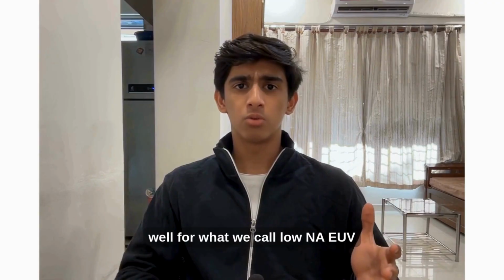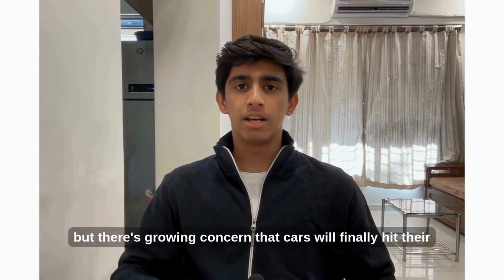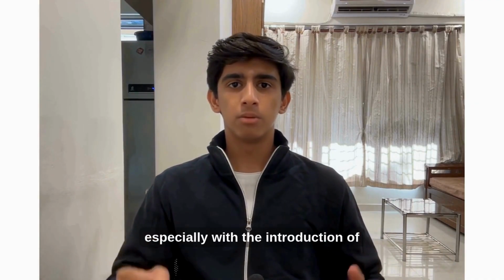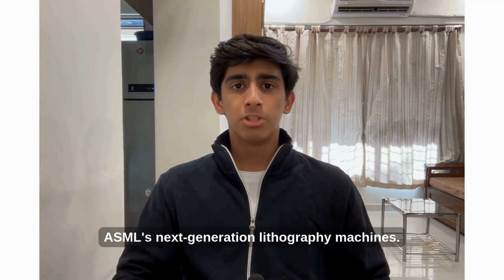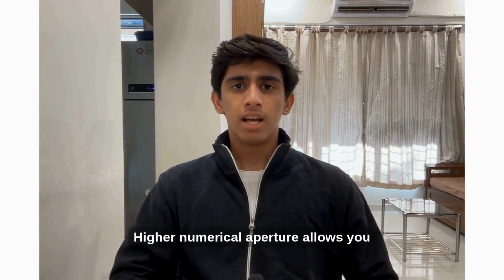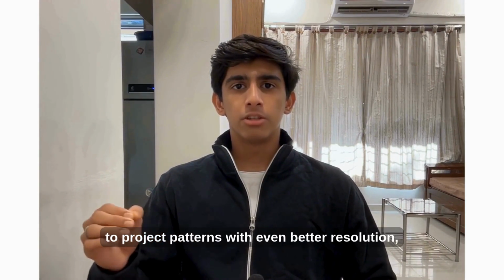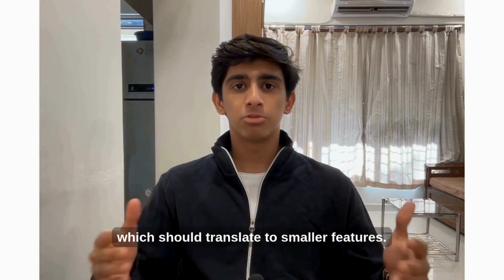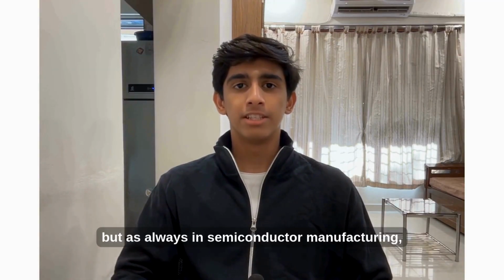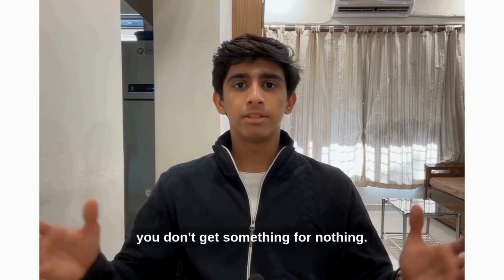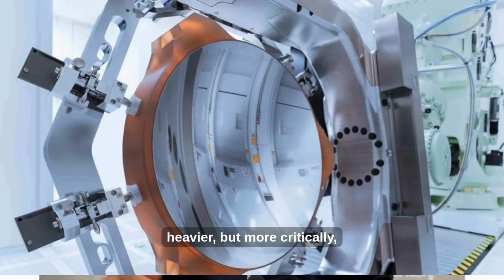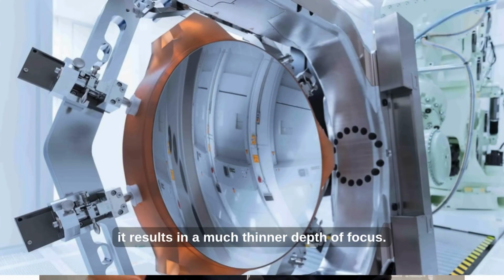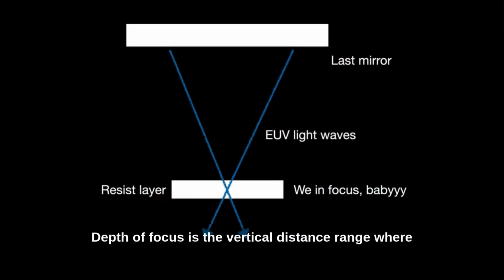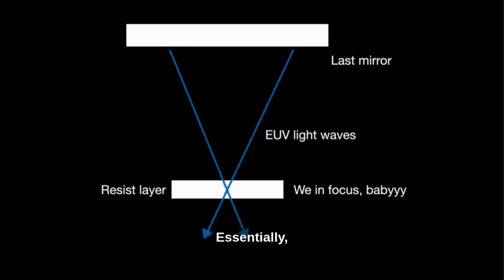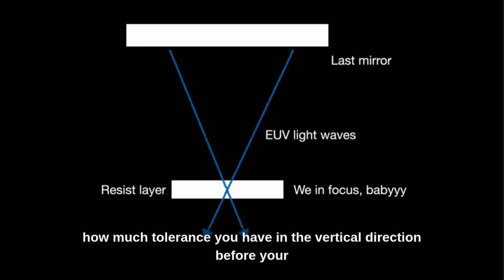Right now, these modified EUV CARs are working reasonably well for what we call low NA EUV lithography. But there's growing concern that CARs will finally hit their fundamental limits, especially with the introduction of ASML's next generation lithography machines, high NA EUV systems. Higher numerical aperture allows you to project patterns with even better resolution, which should translate to smaller features. That sounds great, but as always in semiconductor manufacturing, you don't get something for nothing. Raising the NA means making the mirrors bigger and heavier, but more critically, it results in a much thinner depth of focus. Depth of focus is the vertical distance range where image quality remains acceptable. Essentially, how much tolerance you have in the vertical direction before your patterns start getting blurry.